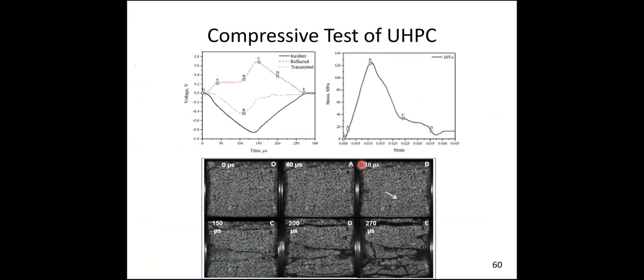So these are some studies for compression testing. Again, you could see how the concrete failed with respect to high-speed loading. This is what I wanted to convey. You can see the arrow mark. This is the place where the crack is initiated, and then it has propagated, and then it led to a number of cracks, and it led to final failure of the sample.